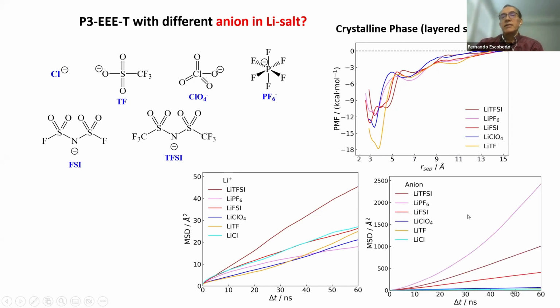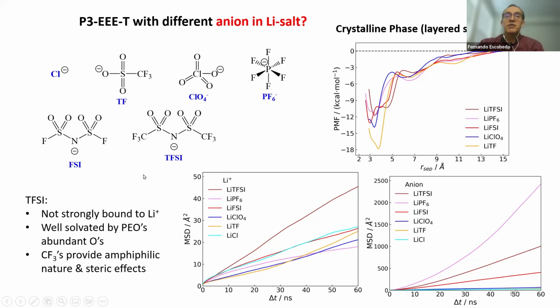So this PF6 seems to be slightly better than TFSI. But as I said, sometimes people care more about the mobility of lithium ions. So in that context, the TFSI will be the best. And so it's interesting because I guess it's designed in such a way that one is not strongly bound to the lithium ions, and yet they have enough oxygens in there to solvate it well,